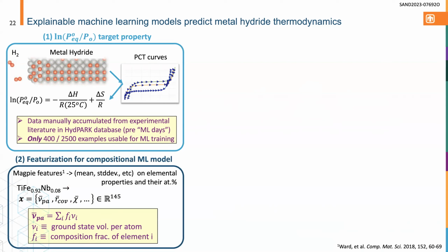The way that you predict that plateau pressure is if you know the enthalpy and entropy of that phase transition. And this is all data that's been accumulated over the years. Sandia has a very strong hydrogen storage program going back many decades, and luckily for us, some people accumulated this CSV file of thousands of metal hydride papers, and did this analysis where they extracted delta H and delta S.